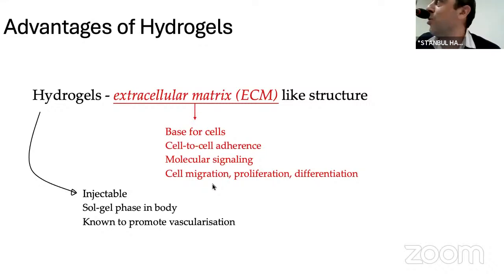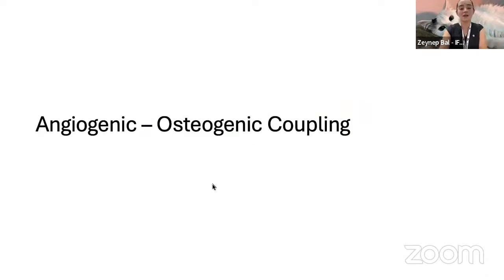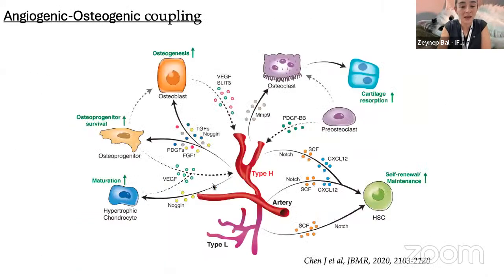What is your advice for hydrogel? What I want to focus on is that osteogenesis cannot be separated from angiogenesis, right? They are coupled together. So if you're going to use core decompression, for example, please design your hydrogel with vascular endothelial growth factor VEGF plus, for example, BMP2.